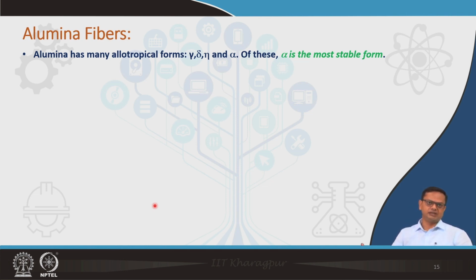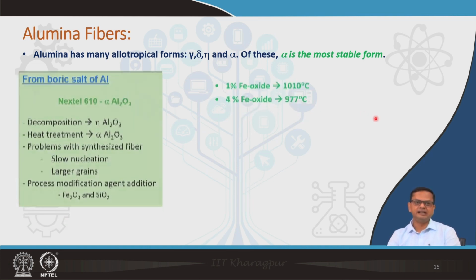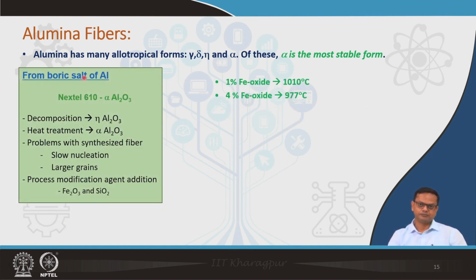In case of alumina fiber, alumina has several different allotropes like eta, gamma, and alpha and others. In that case, alpha is the most stable form, and it also shows fairly good mechanical properties compared to the other allotropes. So, the idea here is to make alpha alumina when you try to make alumina fiber. Now, the starting material here is the boric salt of aluminium. That is the alkoxide, the precursor material, and it can decompose at high temperature by the sol-gel technique, and it gives you eta Al2O3. Obviously, you do not want to stop there. So, you go for heat treatment to get alpha Al2O3, right.